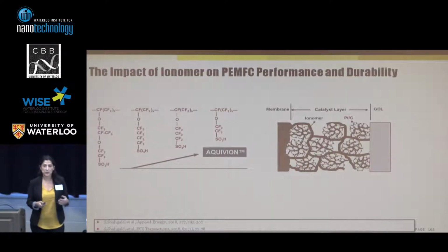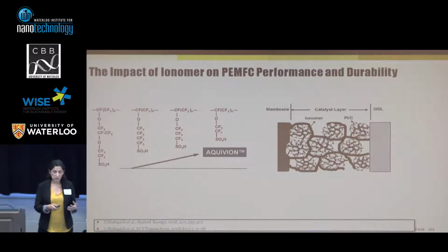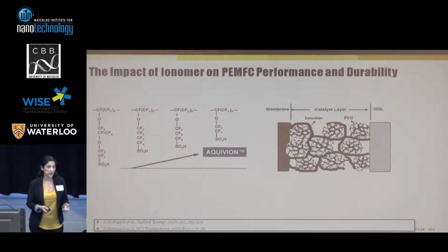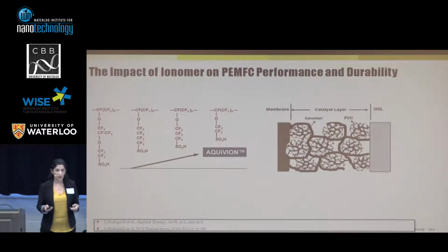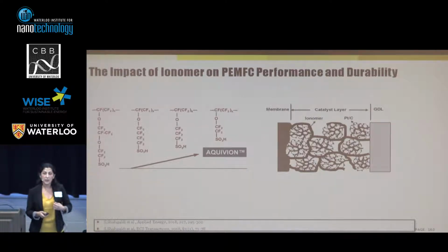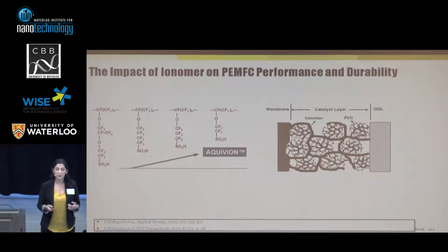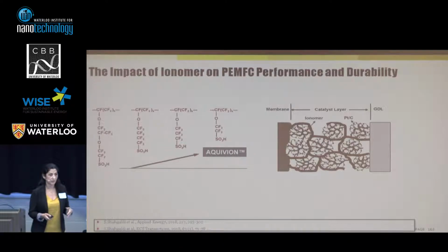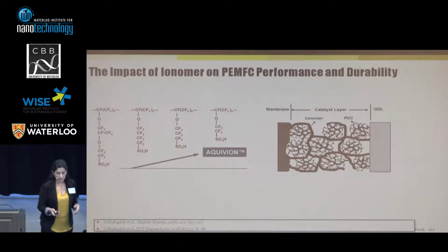Besides the role of the catalyst and MPL, the other component that we have in the catalyst layer is ionomer. That ionomer has two roles. One is ionic conductivity, and it acts as a binder. We find that different ionomers and different ratios of the ionomer have a substantial impact on our MEA performance.